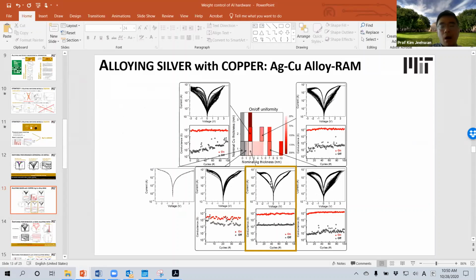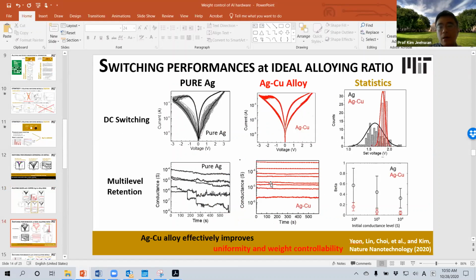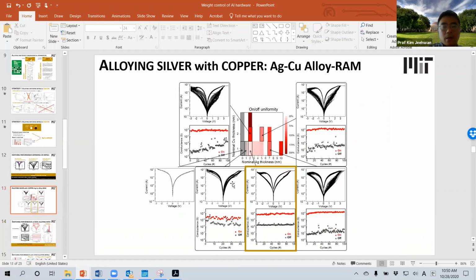Oh, so I didn't add the slide here. We are putting in a Schottky barrier. We've tried to put a Schottky barrier on the silicon. We try to dope the silicon, so then we make some selector in it. So then we can reduce the sneak path by putting in a natural Schottky barrier, because we are making a junction between the silver-copper and the silicon. So we do some p-type doping in silicon. We try to alter the doping level to have a Schottky barrier to use as a selector.